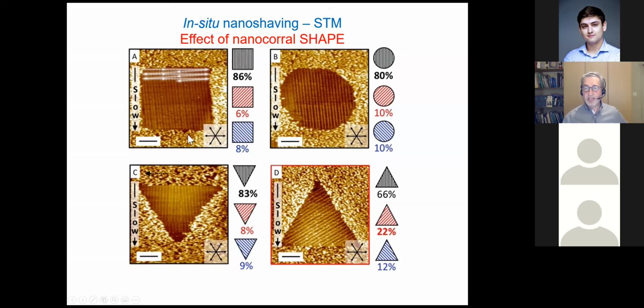If you look here at these square shaped systems, the molecules faithfully align along what we call the slow nanoshaving direction. So the tip moves like this, fast, and goes slow from top to bottom. So the rows align along the slow direction. And that is okay for square, disc-like, and also triangular corals, except if we have a triangular coral where we shave from the apex to the bottom. Then if you look into the statistics, we see that there is a large deviation from the alignment from top to bottom. Why is this?